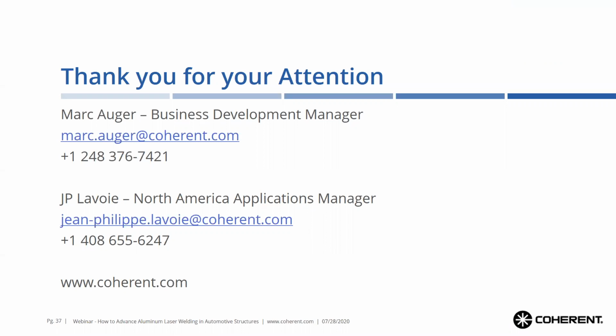Yeah, so this again could go on for quite a while. I'll just try to summarize it a little bit in buckets. We find that for materials like high power aluminum, what we talked about today, in a lot of cases the 70 micron core and 180 micron ring, for example, is a good laser for a lot of these applications in that it offers very high power density and is able to melt these materials very efficiently.